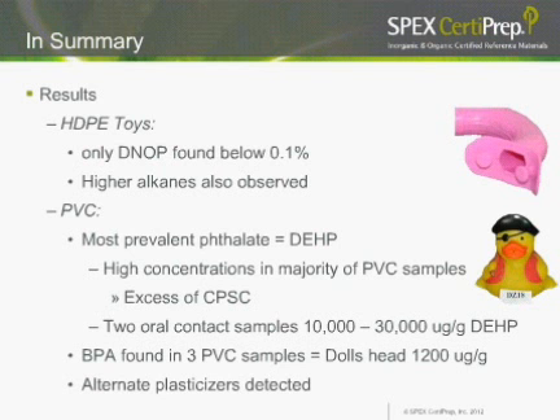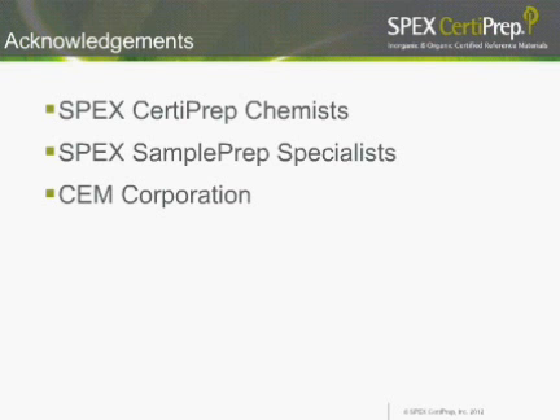We also found Bisphenol A in 3 of our PVC samples, including our doll's head, which topped out at 1,200 micrograms per gram of Bisphenol A. And we found some alternate plasticizers in our PVC. And that is the conclusion of our results.